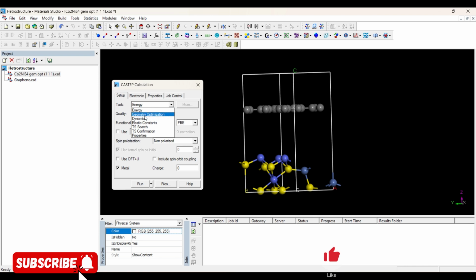task geometry optimization. For this tutorial, I'm going to do express settings, as we have cobalt and nickel, so transition metal, so check this GGA plus U. For this tutorial, I'm going to do non-polarized, but you have nickel and cobalt, you can choose collinear as well, so to calculate their magnetic properties as well. So for this tutorial, I will be doing non-polarized.